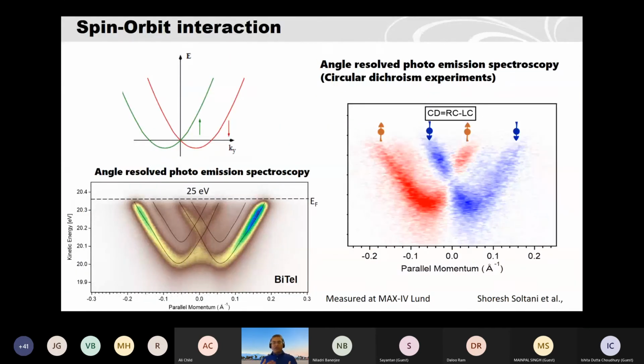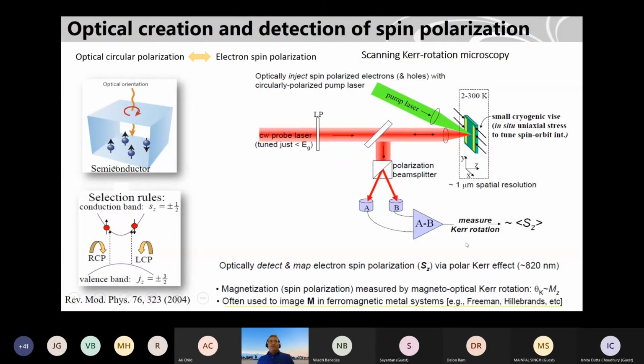Because of this huge spin orbit coupling, over the years it was very difficult to inject spin from the ferromagnet into the semiconductor and detect it also by an all electrical method. It was very challenging to do that electrically. But what people did earlier, you can find this review article if you want to know more: if you have a semiconductor and shine polarized light, let's say left polarized, you can create spin polarization in the semiconductor. In semiconductors like gallium arsenide, they follow the selection rules. With left polarized light you can create, let's say, down spin here. With right polarized light, you get the opposite spins.